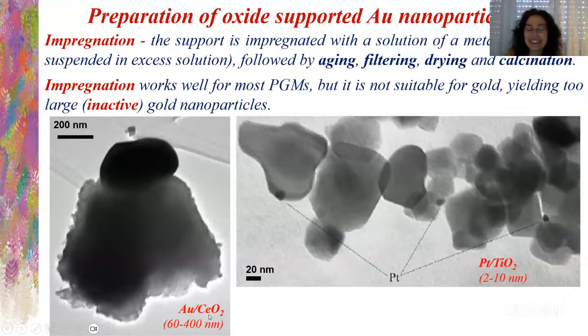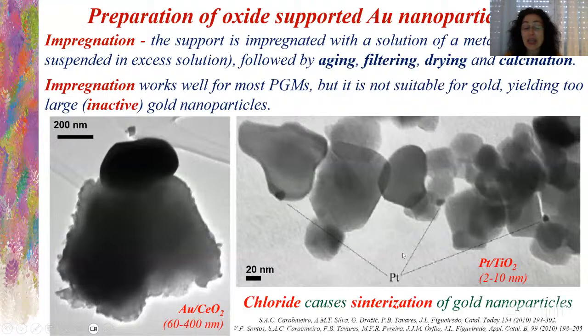This is completely inactive. And see, the platinum nanoparticles, by the same method, are small, so it's quite good. The reason is that chloride causes sintering of gold nanoparticles. They form aggregates, get together, and so become inactive. So we have to use other methods to prepare gold catalysts.